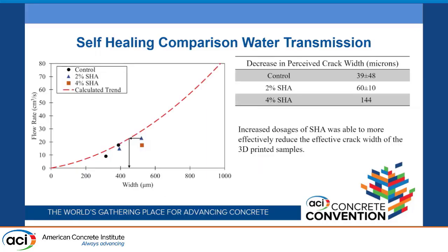So we have all of our samples here—our 4%, our 2%, and our controls—relative to our expected trend line that we calculated with that 0.9 R squared value. We then backtracked our effective crack widths by taking our measurement of water flow to the trend line, and we were able to calculate our decrease in perceived crack widths.